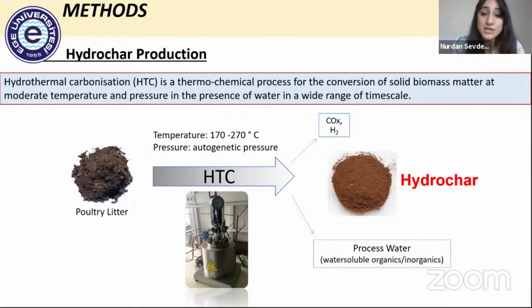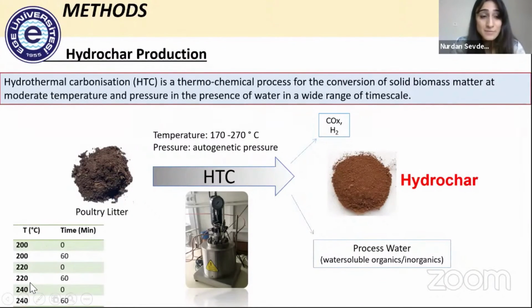After hydrothermal carbonization, we have three products: gas, liquid, and a solid one, which is named hydrochar. We carried out our experiment in a stainless steel autoclave at 3 different temperatures and 2 different reaction times.